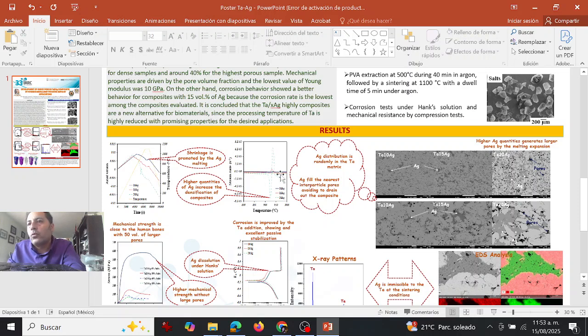The more silver we add, the higher the densification of the compact, which is mainly due to the liquid phase formed inside the samples. In the microstructure, we can observe that the silver is distributed randomly inside the samples, and we found that the samples with larger quantities of silver create additional porosity. This is because we have swelling during the melting of the silver.